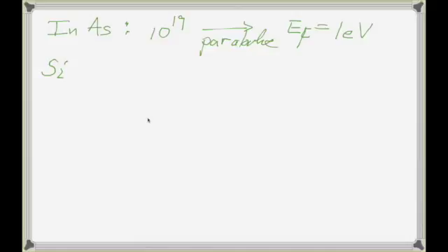And you need to worry about this in silicon when the doping is greater than or about equal to 10 to the 20th. When the doping becomes greater than that, if you don't make a correction to your usual parabolic model, your Fermi level starts to be somewhat off.